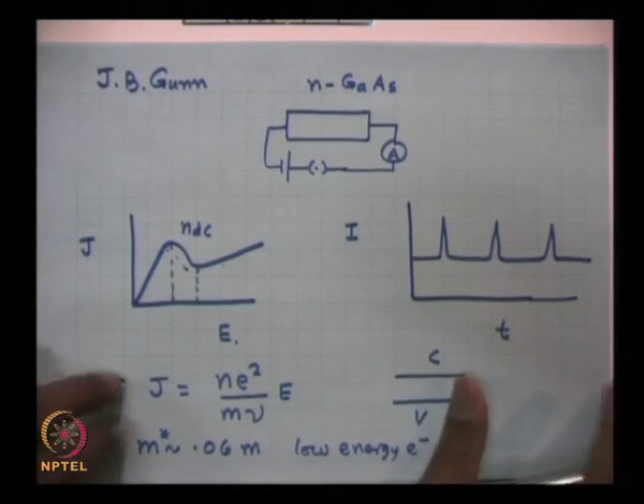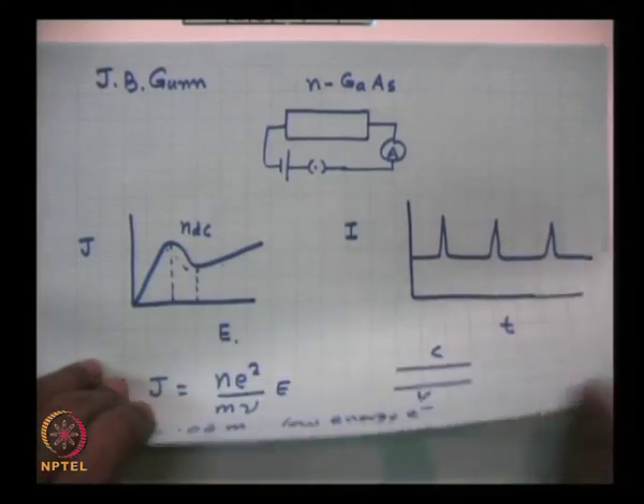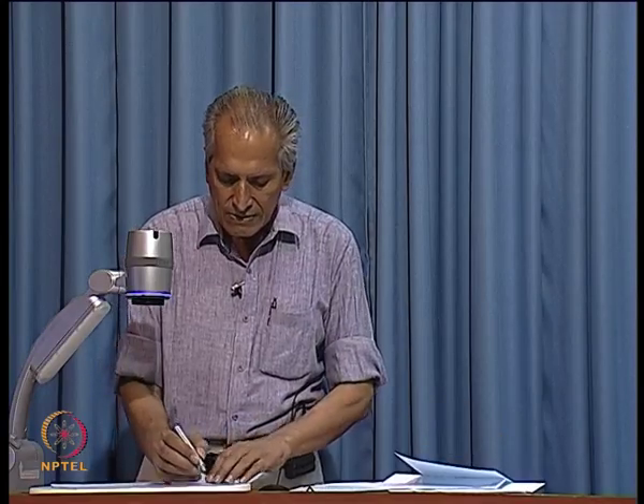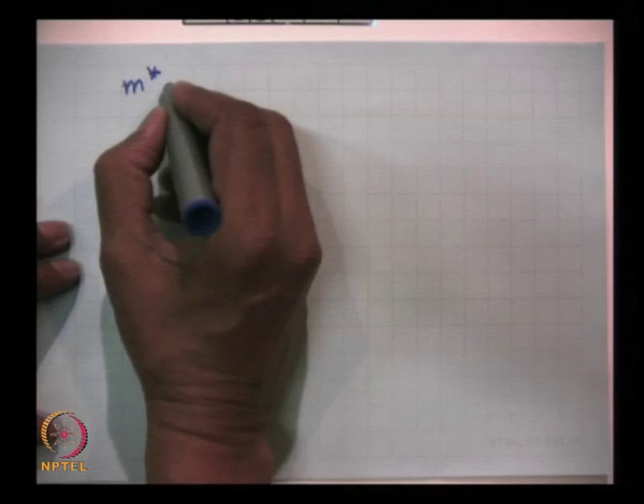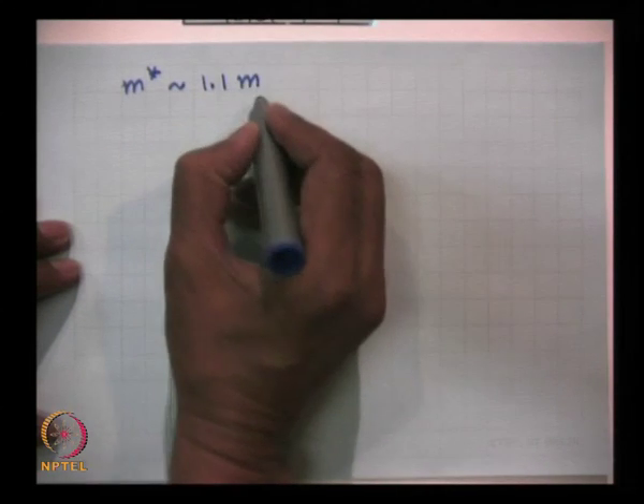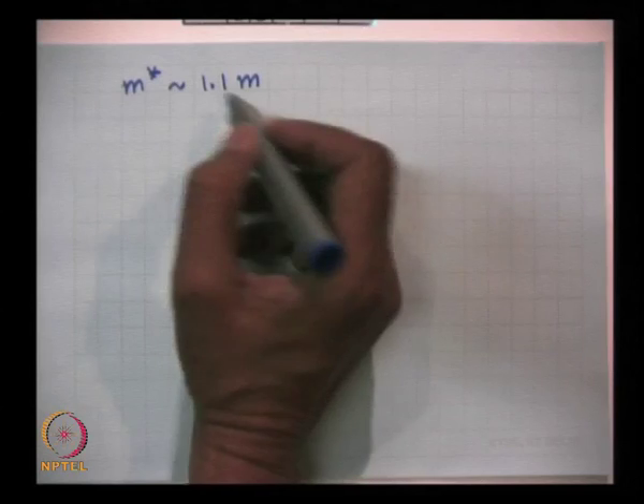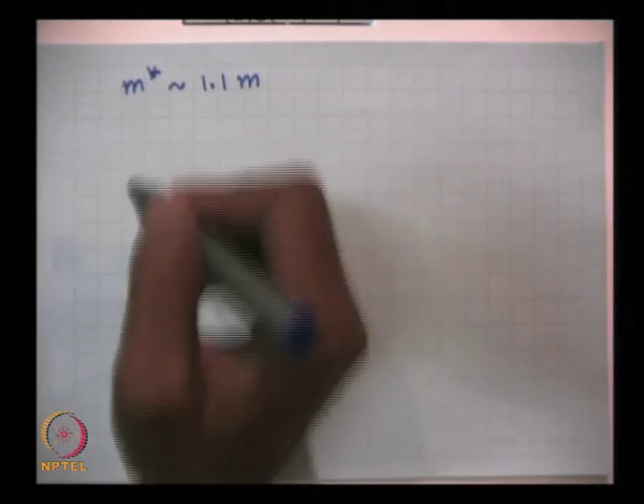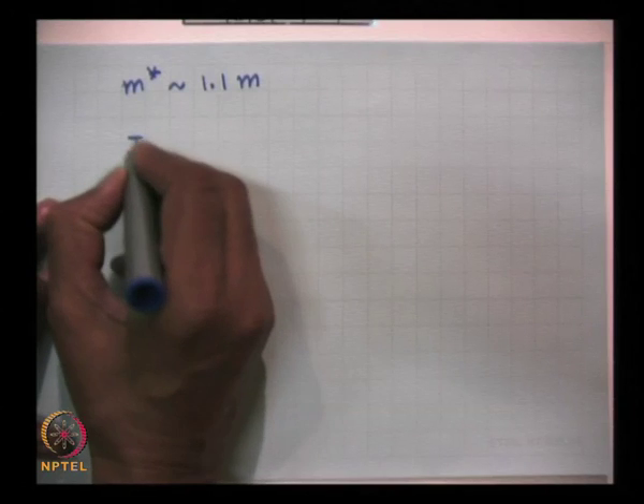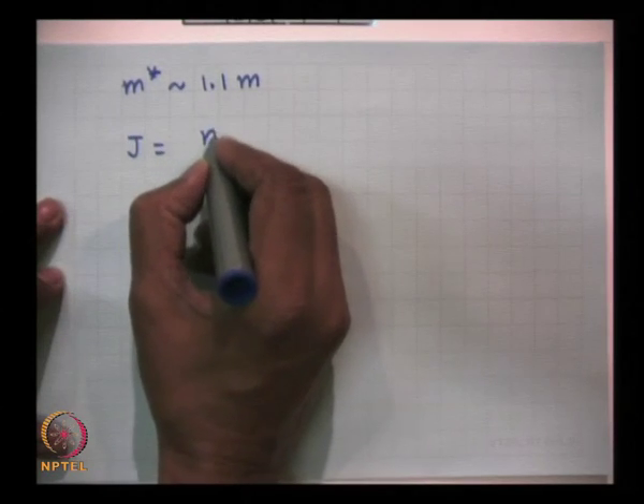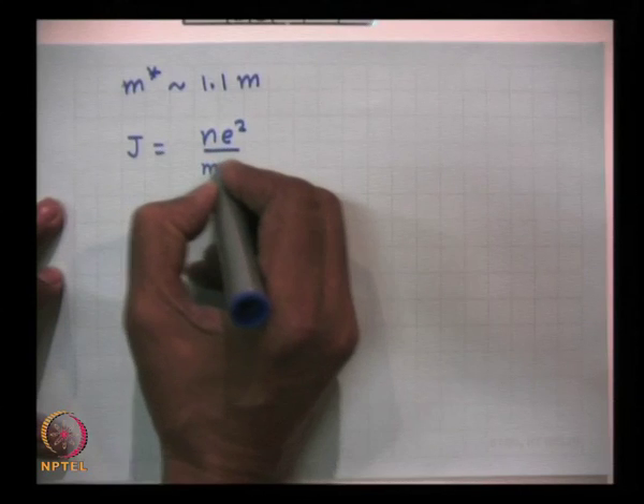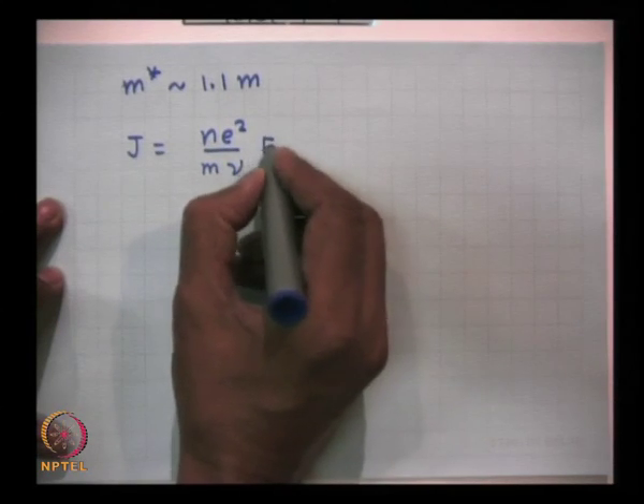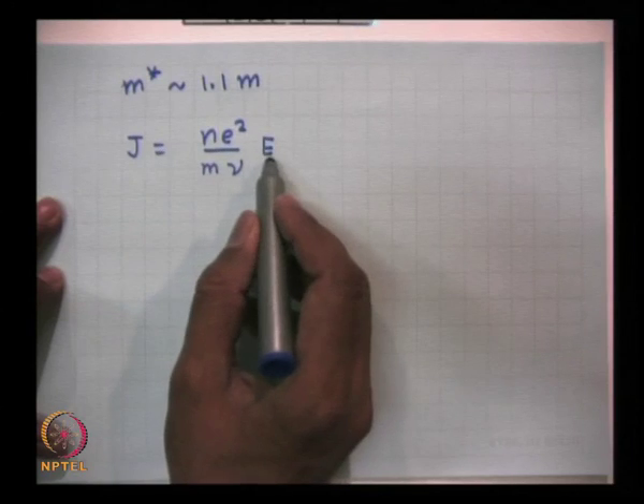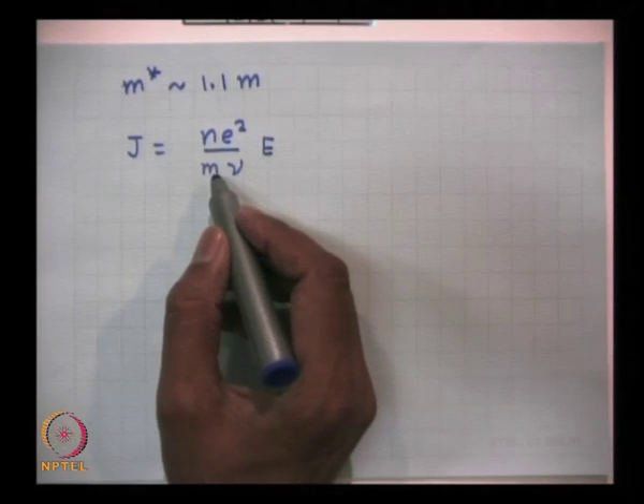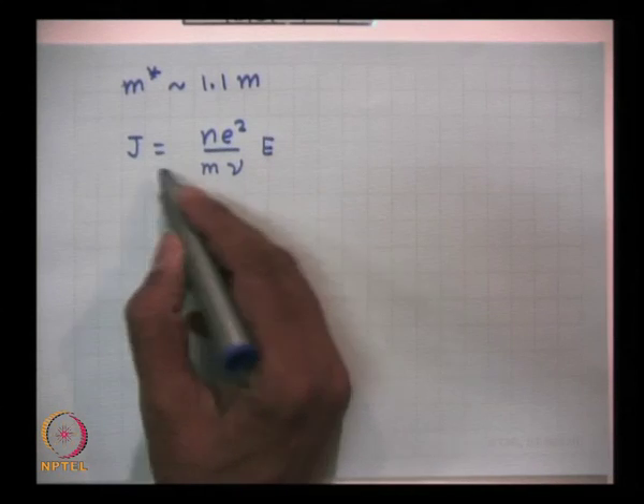Whereas high energy electrons in the conduction band have a higher effective mass, and that effective mass m star is of the order of 1.1 m, where m is the free space electron mass. So, what is happening here is that if you look at the expression for J, which is equal to n e squared tau upon m star into E, the electrons at low electric fields have low energies and consequently mass is low. So, conductivity is large, current is large.